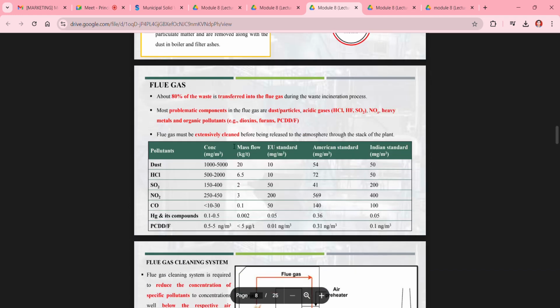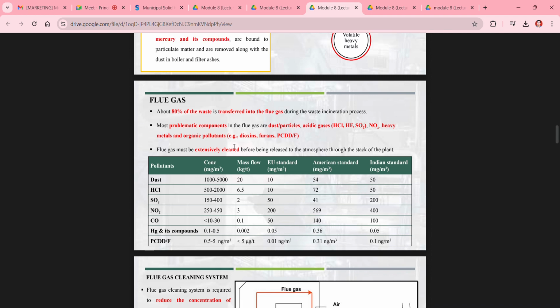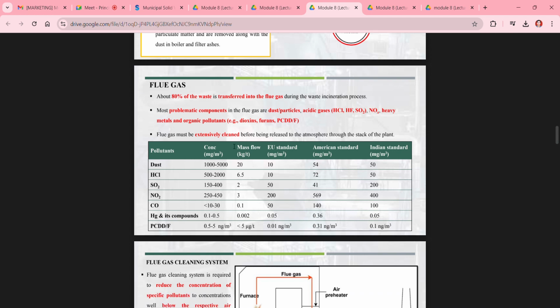So about 80% of the waste is transferred into the flue gas during the waste incineration process. The most problematic contents in the flue gases are dust particles, acidic gases like HCl, HF or SO2, NOx emission in the form of NO2 or N2O, heavy metals and organic pollutants like dioxins, furans and PCDD/F. Flue gas must be extensively cleaned before being released to the atmosphere through the stack of the plant.